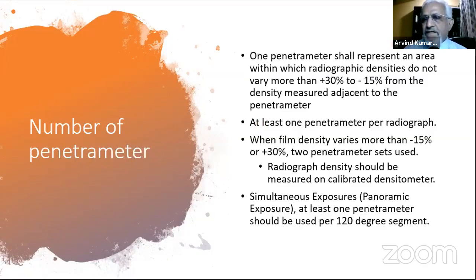And if there is a variation, you have to reject the radiograph, or next time you do it, if there is a problem in the technique, you have to put 2 penetrameters, giving a proper evaluation. And for the panoramic technique, there is no need to place an IQI on each film. What you need to do is divide the circumference into 120 degree segments, and in each 120 degree segment there has to be 1 penetrameter, as the code says.